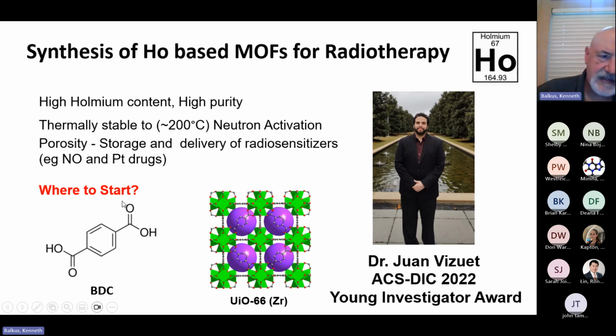So we said, well, okay, let's see if we can use holmium and make a stable metal organic framework. One of the reasons he picked this particular MOF is that it is very thermally stable. When you neutron activate holmium, the reactor heats up. It could be 150 degrees or more. And so you have to have a metal organic framework that will withstand those temperatures.